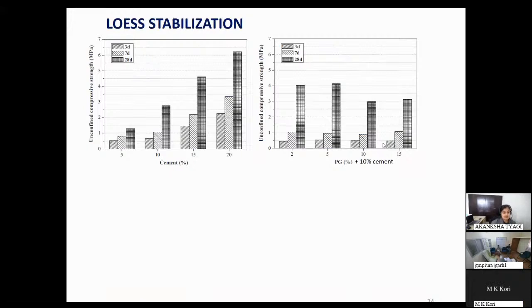This study was done by the researchers Gu and Chen, and it is a very recent study, published in 2020. We know that when we add cement, there is almost a linear increase in the strength of cement stabilized loess. But they also used phosphogypsum plus 10% cement. They picked 10% cement and added 2%, 5%, 10%, and 15% of phosphogypsum.